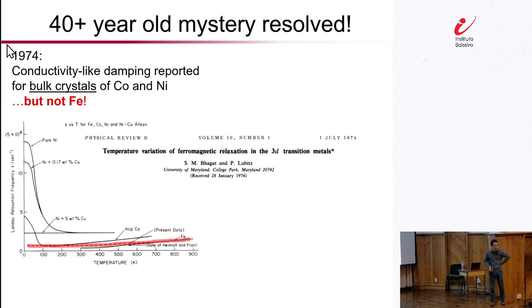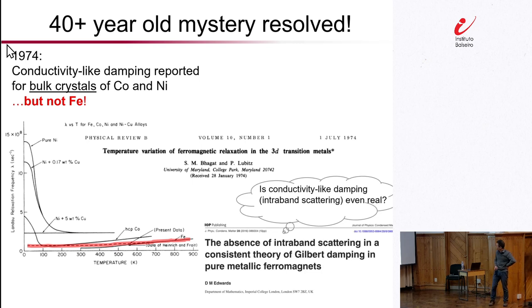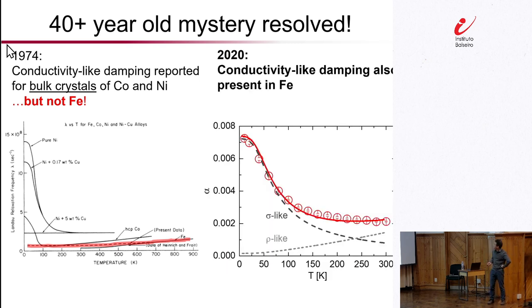And this remained the case for the next 30, 40 years. So it remained quite a bit of a mystery in the field, such that some theorists began to wonder whether this conductivity-like damping, this intraband scattering, even exists. But what our study, which was published in 2020, was able to achieve was to show that there is also conductivity-like intrinsic Gilbert damping in elemental iron as well.